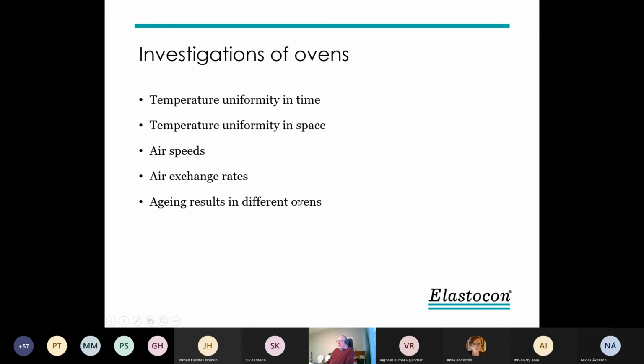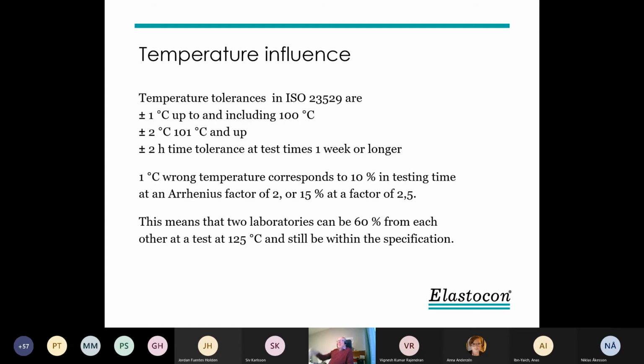We then decided to investigate different ovens and their uniformity in time, uniformity in space, air speeds, air exchange rates, and practical aging results in different ovens. If we look at the tolerances we have in the standards, we tolerate plus minus 1 Celsius up to and including 100. Over that we have plus minus 2 Celsius. And for time we have plus minus 2 hours if the test time is 1 week or longer.